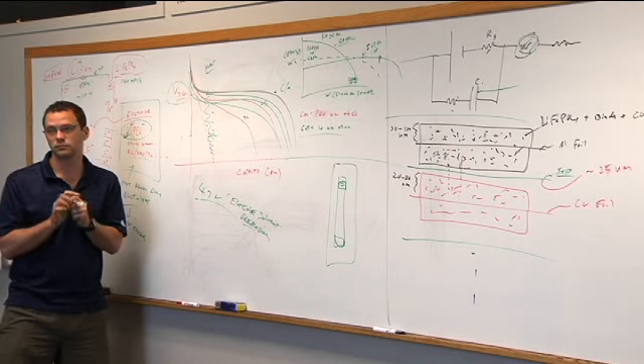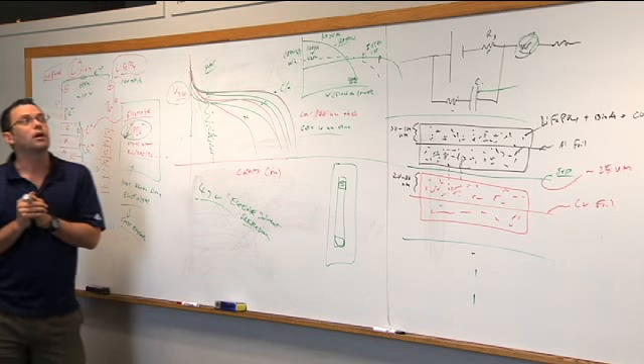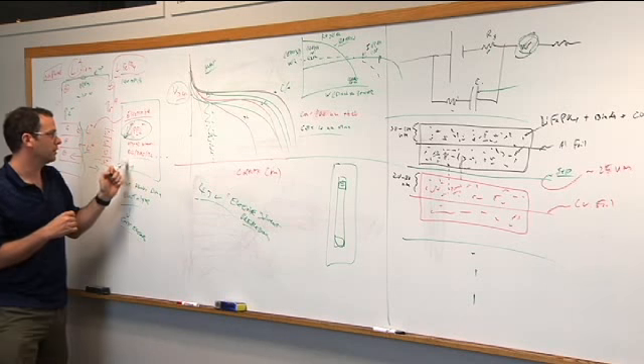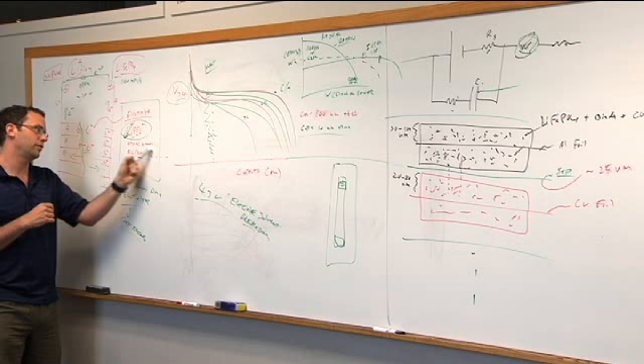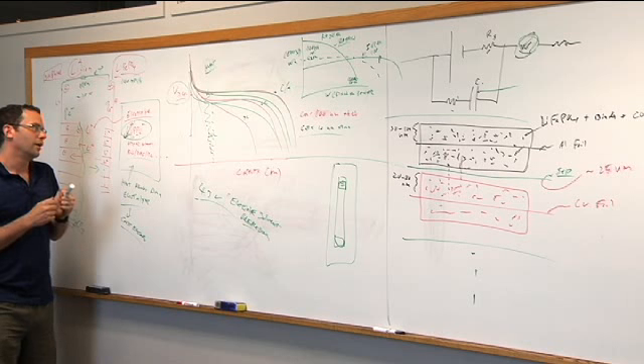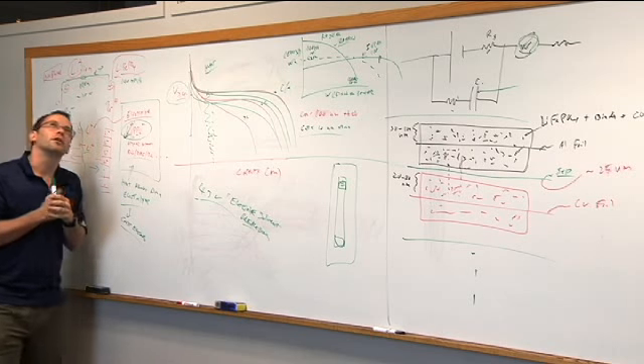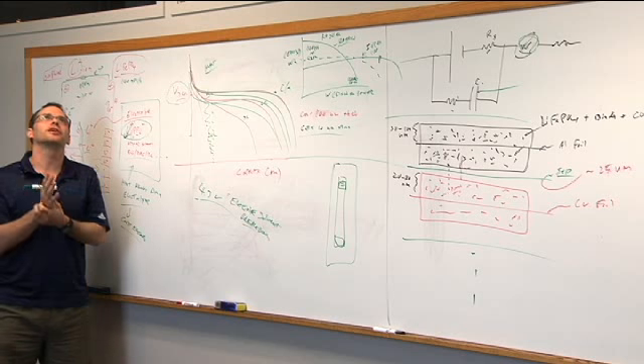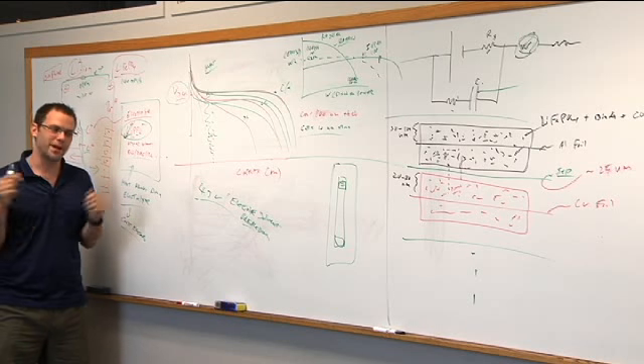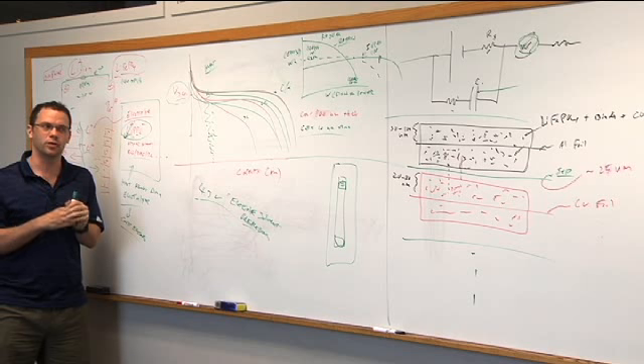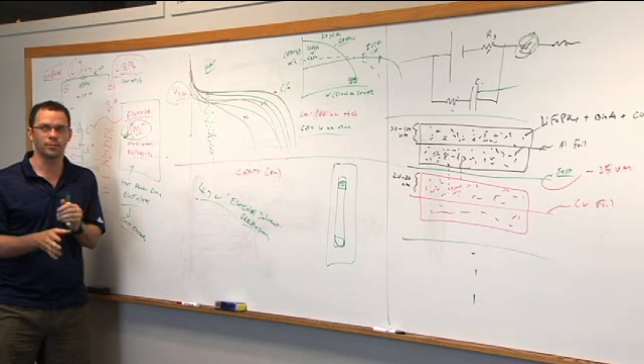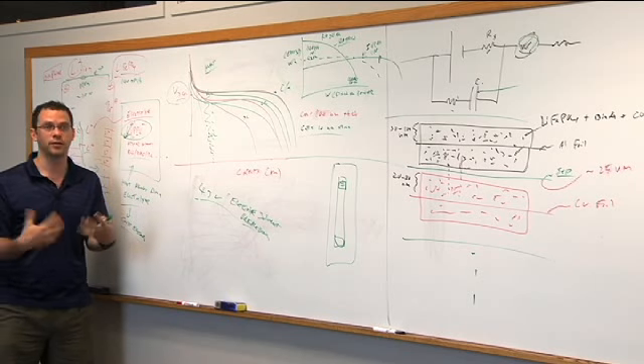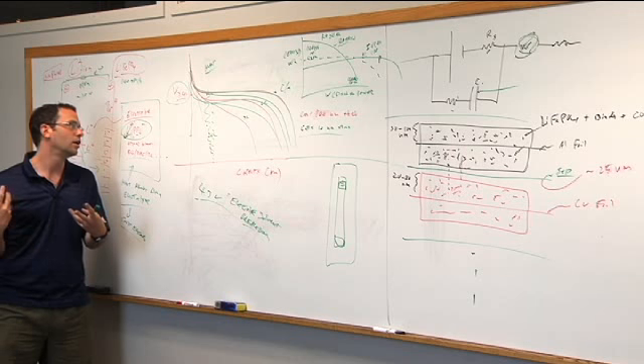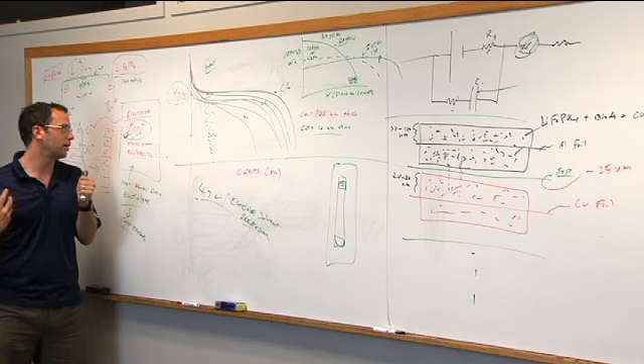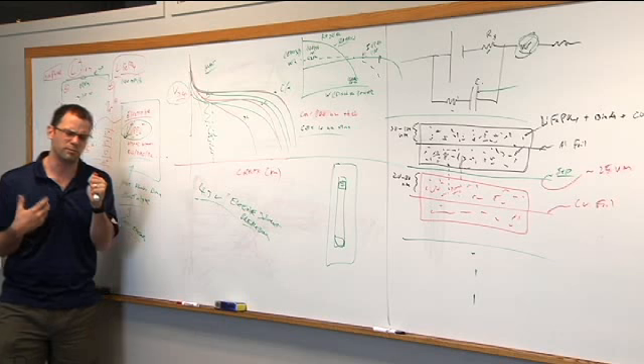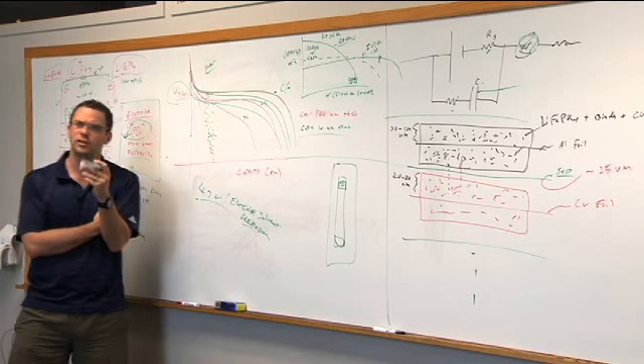What about lower bounds on temperature? Oh, that depends also on the solvent. Everything is dictated by this solvent. And here's the thing, too. There is cold crank, like when I first bias it, and then there is what happens after I run at a particular current for a couple minutes, because it self-heats, right? That's the good news about batteries, especially these batteries: they will actually self-heat. But with this off-the-shelf kind of stuff, you could probably go to minus 10, minus 20 C. I'd say minus 20 C is reasonable.